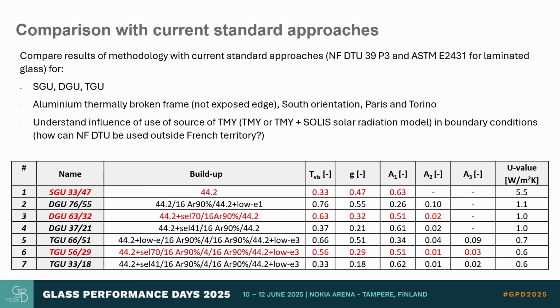What I'm presenting, we did only for an aluminum thermally broken frame with a non-exposed edge, for a south-oriented facade in Paris and in Torino, in Italy. Paris because it was in French territory, so we could compare like for like with the French standard. And also because it was important for us to understand the influence of how I choose the boundary condition in my thermal shock risk assessment, in which we use 2 sources of climatic data for our dynamic model. One is TMY with real sky, and one is a TMY with a model of only clear sky, which is the TMY plus Solis. That means that in that TMY, I'm considering that I have no clouds. I always have clear sky, while in the other one, I have the real sky with the clouds.